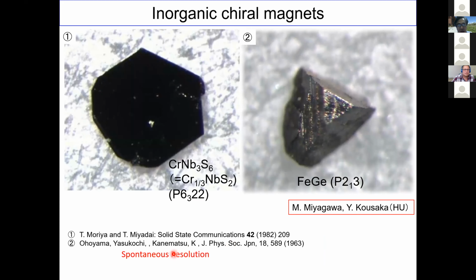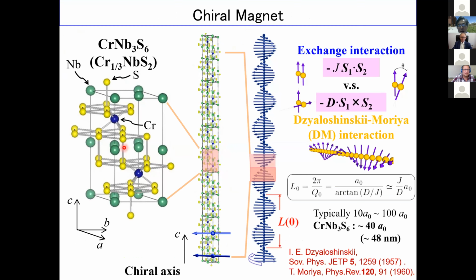Then let's consider the experimental evidence. I have already shown this sample many times, so I will go quickly. We are talking about the left side, the chromium niobium sulfur case. This compound crystallizes in a chiral space group, P6322, and the niobium and sulfur make a layer, and the chromium is intercalated between layers. The chromium has a spin of 3/2, and they make a helix by the Dzyaloshinskii-Moriya interaction, which comes from the crystal chirality. We already know the pitch of the helix, and we have already observed these properties.